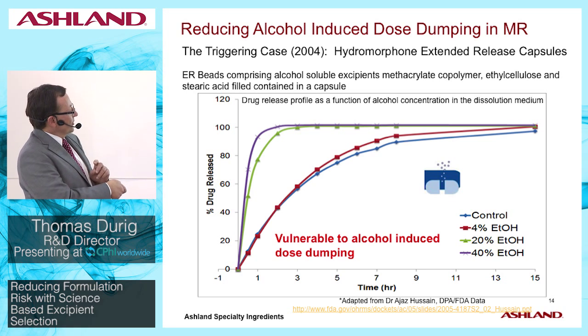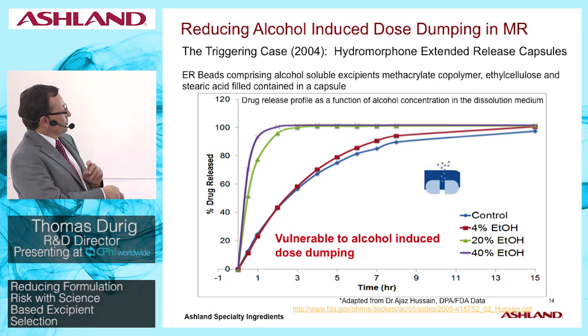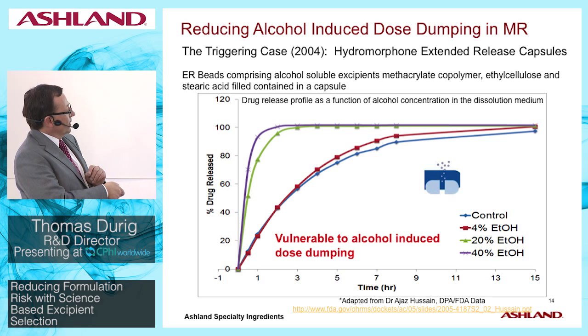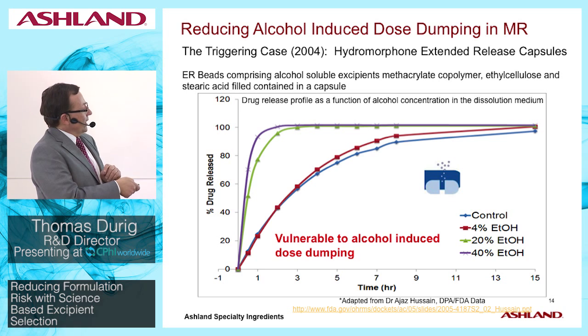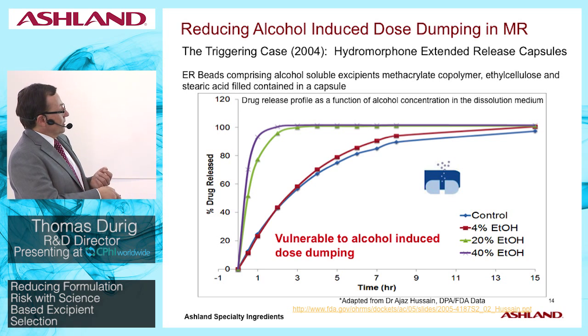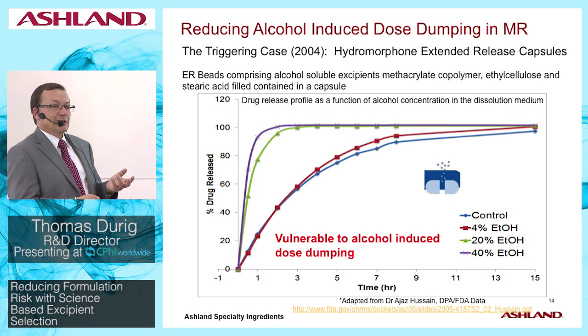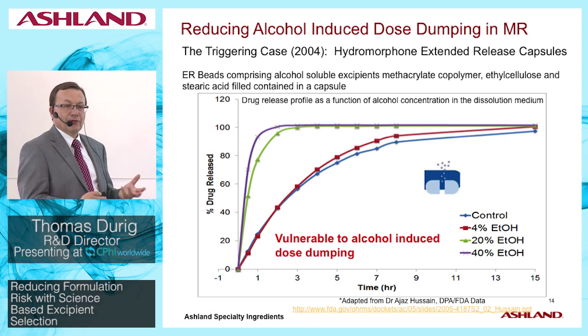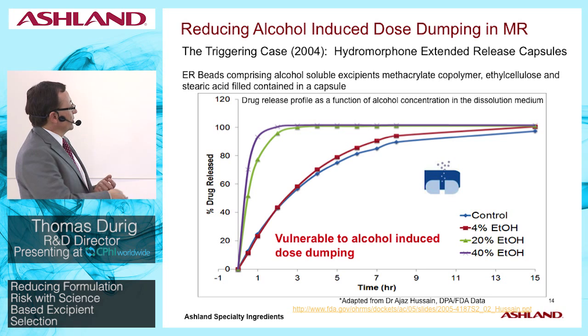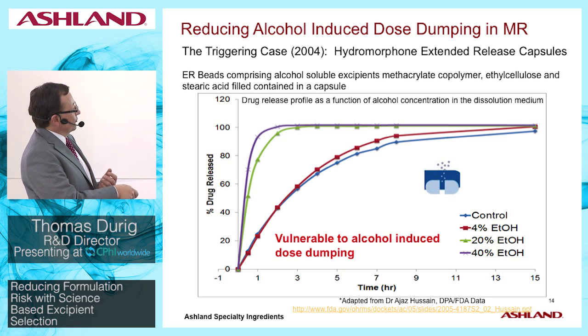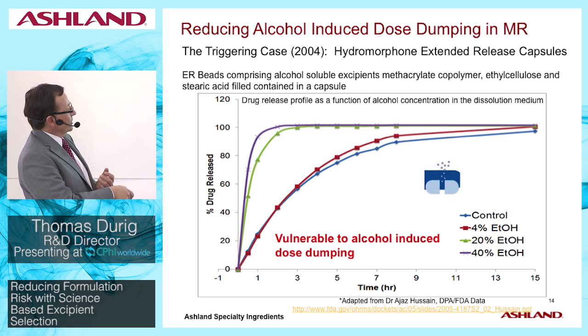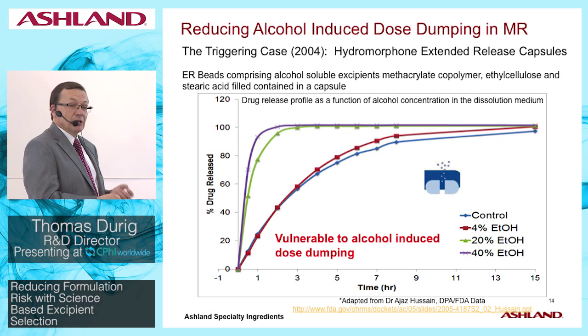And as is illustrated in this particular dissolution profile, based on studies from FDA at the time, the typical release profile is shown here. The desired controlled release profile is the blue line. And then as one increases the alcohol content in the dissolution medium, up to 40%, which simulates a relatively extreme case of very large amount of alcohol ingestion, we can see that the dosage form moves from being a modified release, controlled release one, to essentially an immediate release one.